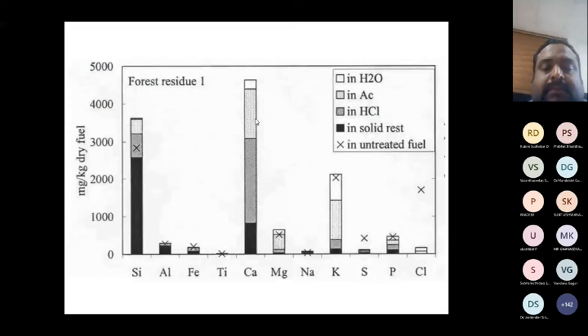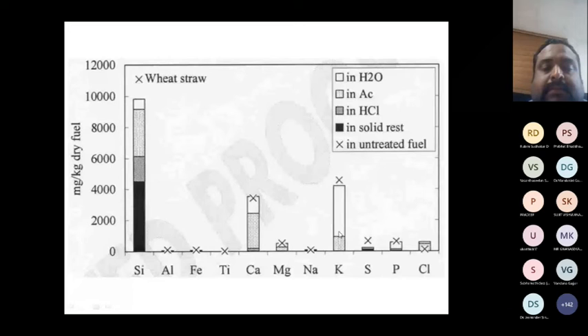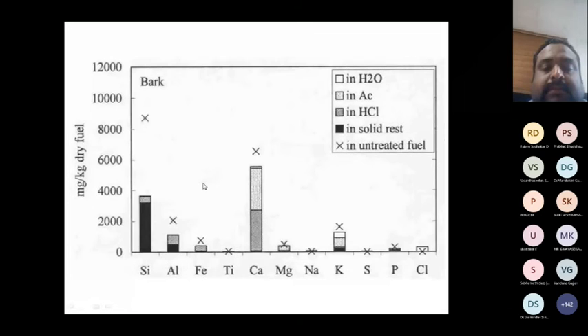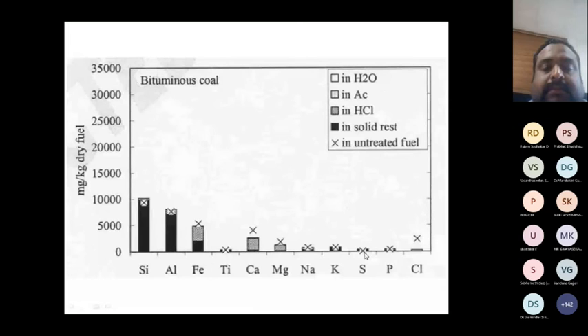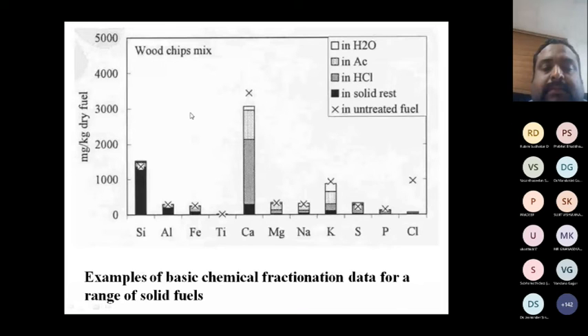So if you see some of the results here, forest residue. This is water leachable, this is ammonium acetate leachable, this is hydrochloric acid leachable. This is rest. So calcium, in forest residue, has a substantial amount of ammonium acetate soluble. Similarly potassium. Wheat straw, calcium and potassium. Bark, calcium, potassium. Coal, nothing is there. No calcium. They are all very insignificant. So the wood chips, again calcium, potassium. So calcium and potassium are examples of basic chemical fractionation data for a range of solid fuels.